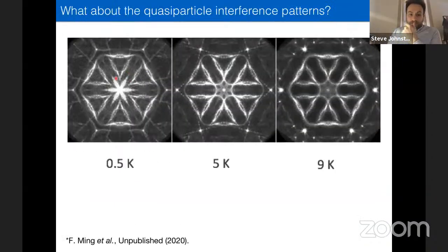And so again, what we think is that this is really evidence that what we're seeing is a chiral order parameter in the system. And this remnant that you're seeing above TC may actually just be because we have fluctuating superconductivity in the system.